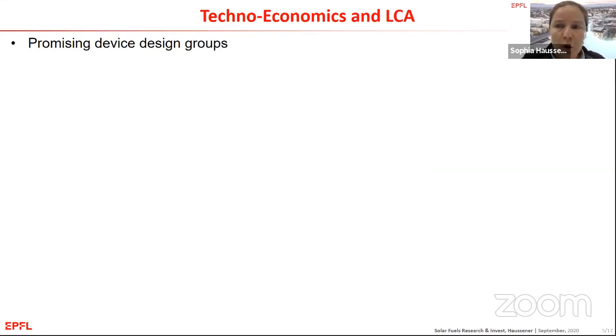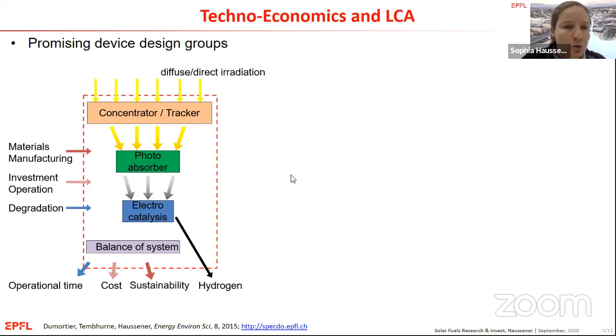Promising device groups is what we try to define like this. And in order to do that, we basically made a high-level estimate of what would be required for such a photoelectrochemical device, in fact, now system, in order for it to be workable. And so you would feed the system with information on the irradiation condition. You would feed the system with information on the materials and how you manufacture them. In order to get an idea on sustainability, you would feed it with cost parameters, and you would feed it with degradation information so that you can access information on operational time, cost, sustainability, and hydrogen production rate or efficiency. And so that's what we did.